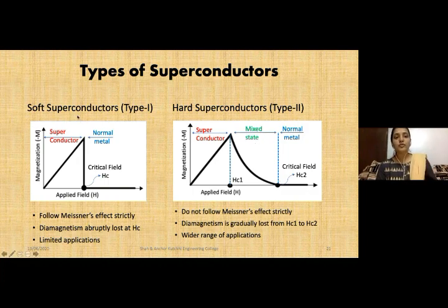Now for type 1 and type 2 superconductors, again you can see the diagram, a graphical representation of field versus magnetization. In diamagnetism, if you remember, I showed that as the magnetic field goes on increasing, the magnetization also goes on increasing. Now this is a perfectly diamagnetic behavior. When a material behaves like a perfect diamagnet, it is a superconductor, because superconductivity is always protected by diamagnetism. But you will see that at the critical field, this diamagnetism is lost. When the diamagnetism is lost, the superconductivity is not protected, and if it is not protected, then the material becomes normal.